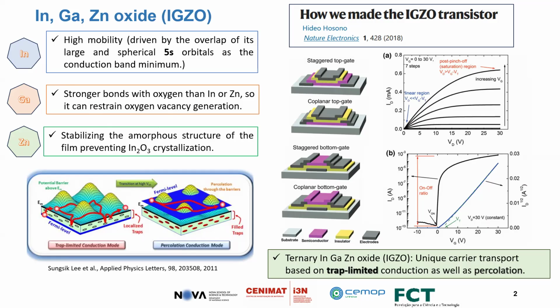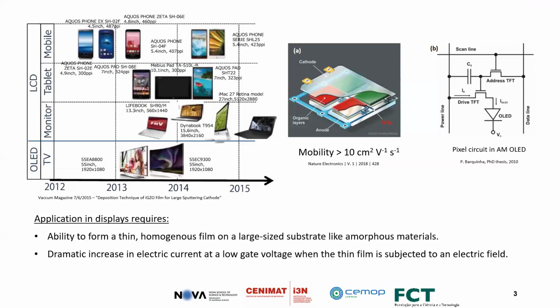Talking about the mechanism of this material, it has trap limited conduction. It is in the trap limited conduction mode, and then up to a certain threshold voltage, which is shown here in one of our typical transfer characteristics of the transistor, it starts to go into percolation conduction mode, which depends on V on, the threshold voltage of the transistor. Usually the transistor has a very large on-off ratio, as we can see here. And this is a typical output characteristic of the devices that we use. We can have different structures, like a coplanar one, a staggered one, and top and bottom gate, depending on different applications.